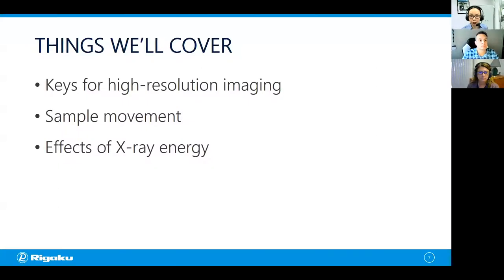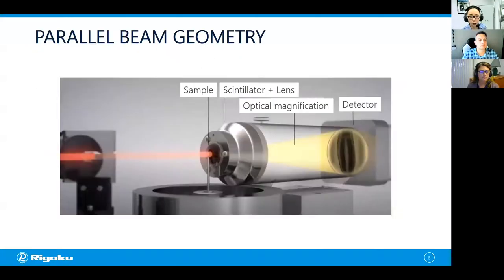So before I show you the instrument we're going to use today, let me just show you this slide to explain the geometry we're using. So we are using parallel beam geometry, which is very suitable for high resolution data collection. When I say high resolution, we're talking about less than a micron resolution, submicron, 1 or 2 micron resolution imaging. So you have the X-ray source on the left. It is outside of this view in this slide, and you take a relatively small X-ray beam and it goes to the sample, which sits in front of the scintillator, which converts the X-ray beam into visible light so that we can use just regular optical lens to magnify the image before it hits the detector. So this is how a parallel beam geometry is constructed.